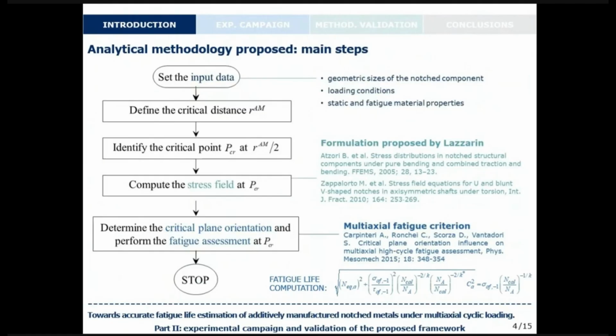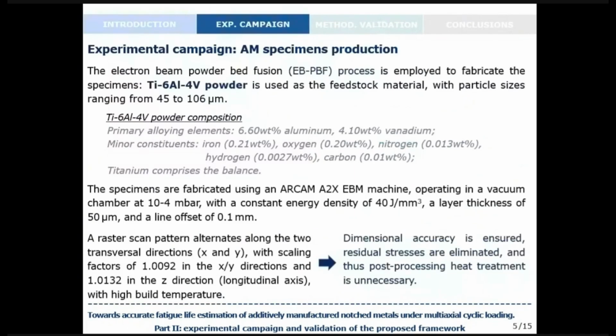So here are the main steps of the methodology proposed. I will go very quickly again here because you already saw these steps in the previous contribution. So we have some input data to be set that are these ones here. Then we define the critical distance R_AM by employing the equation in the previous slide. Then by means of this value, we identify the critical point at a distance half of R_AM on the notch bisector line. And at this point, we compute the stress field, we determine the critical plane orientation, and we perform the fatigue assessment by means of the Carpinteri et al. criterion.